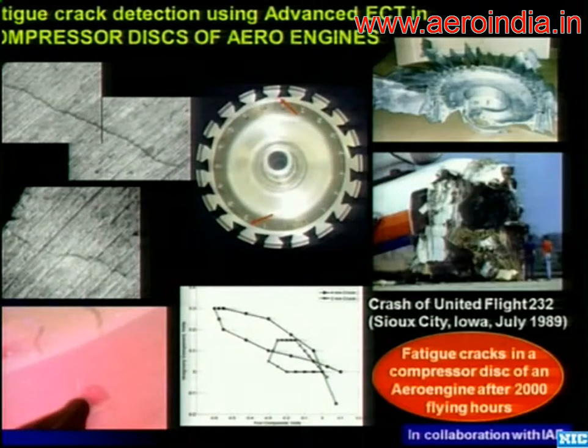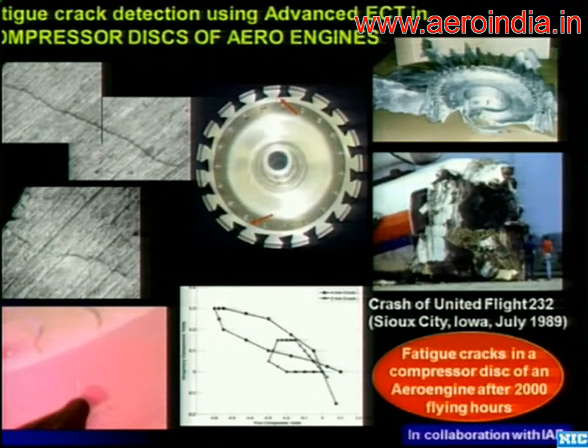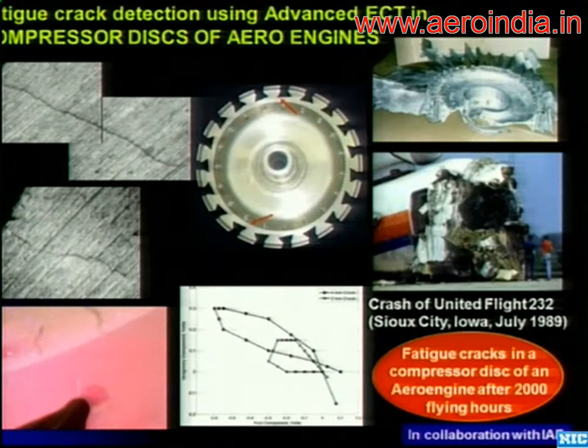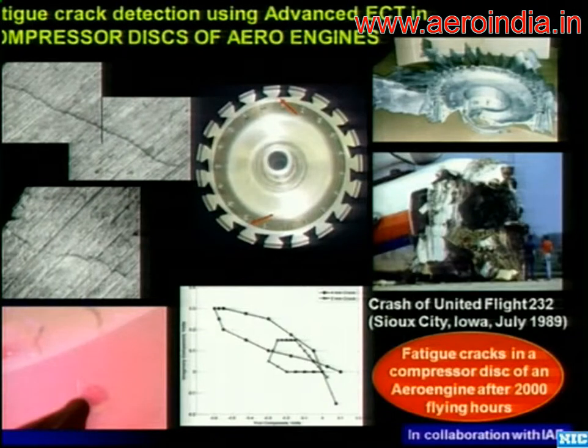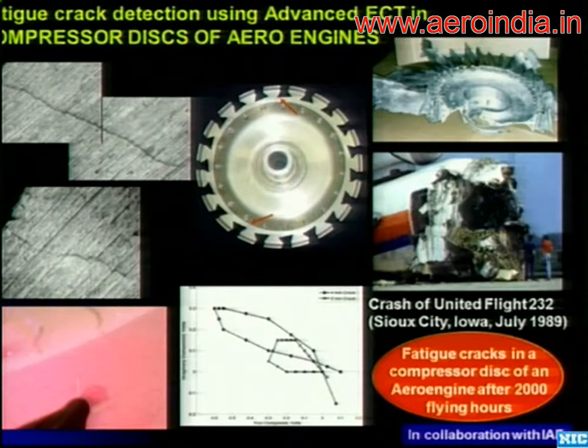The solution was either to reduce the mean time between inspections, which would increase aircraft downtime, or to enhance the sensitivity of defect detection to detect a smaller defect so the crack will not reach critical size before the next inspection. We developed an advanced eddy current-based technique capable of detecting not a 4mm surface equivalent crack but a natural 2mm surface crack using multi-frequency eddy current testing. Once this enhanced sensitivity inspection procedure was introduced, we had no further failures in compressor discs while maintaining the same inspection interval.